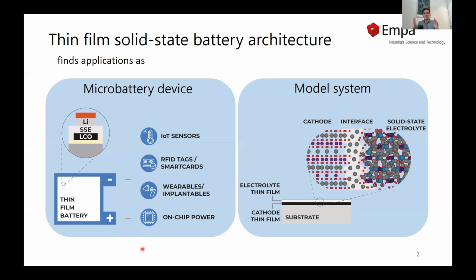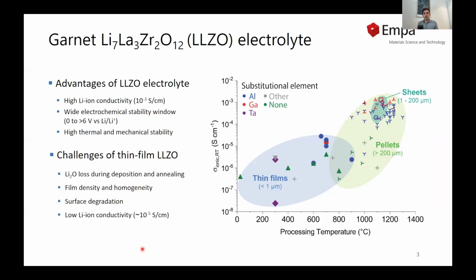For example, in this work, we investigated the interface between the LLZO lithium garnet solid electrolyte and a common cathode, lithium cobalt oxide, in such a model system. The lithium garnet LLZO solid electrolyte has become popular in the research community and also in industry because of its advantageous properties, with ionic conductivities above 1 millisiemens per centimeter, and most remarkably, it has a wide electrochemical stability window, being stable against metallic lithium and high potential cathodes. Moreover, its thermal and mechanical stability make it a promising material for building safer solid-state batteries.